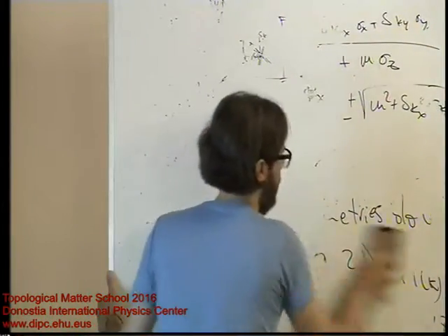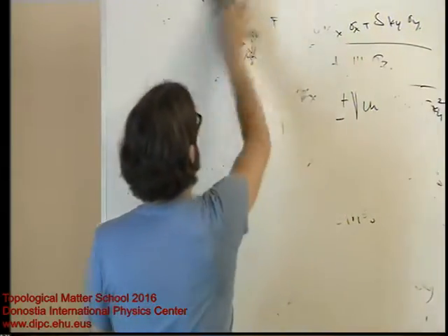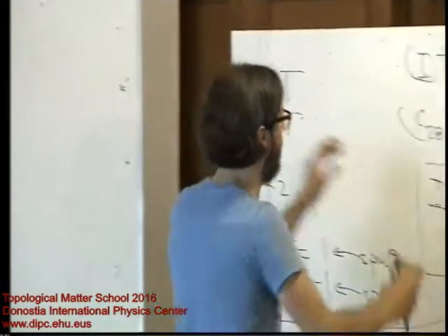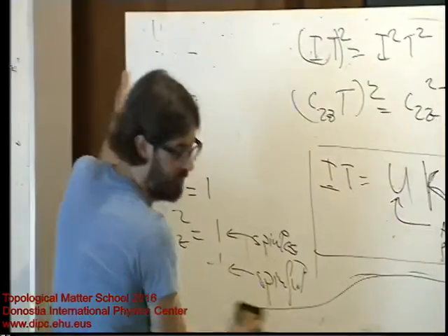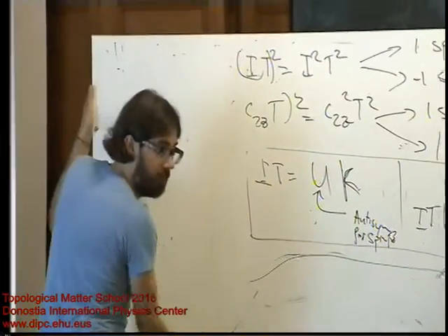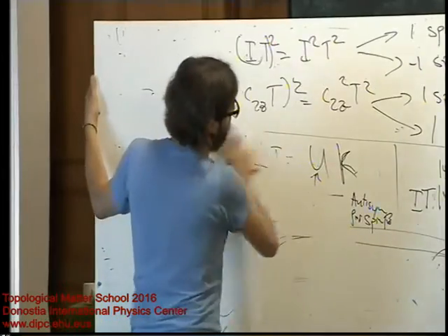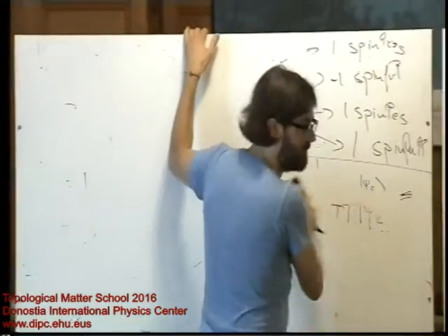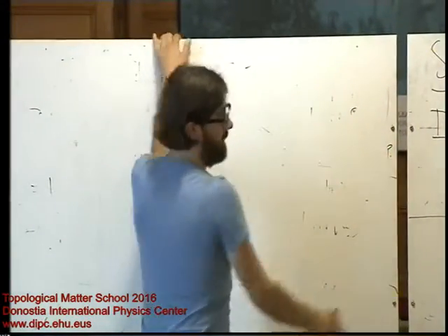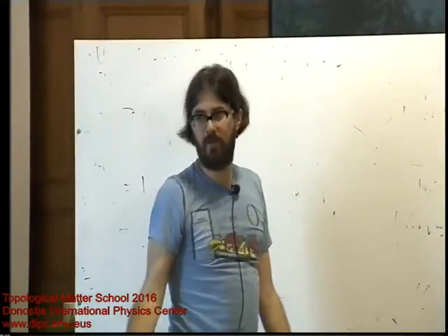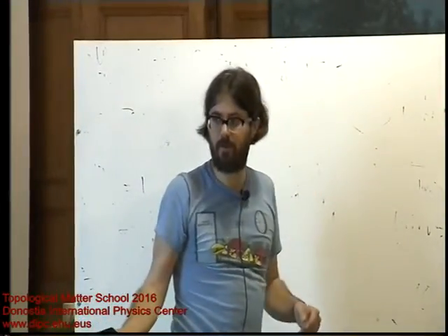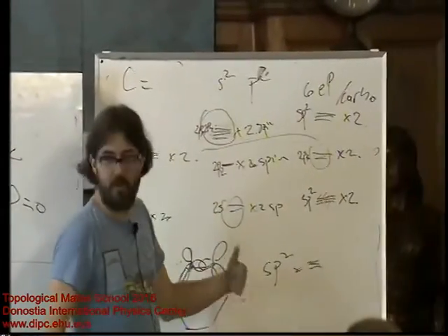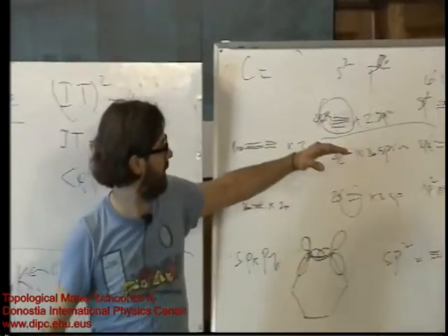So now that I know that my Fermi level sits in the pz orbitals, in the middle, this is not a matter of convention. This has to happen if I have sp2 hybridization, and sp2 hybridization is the chemistry content of this problem. Everything else is group theory in graphene. The chemistry content is that chemists tell me that carbon atoms sp2 hybridize. If the S level of the carbon atom was much lower than the P level, it wouldn't sp2 hybridize. You'd have an insulator. If carbon somehow had the S orbital much lower, sitting here, it wouldn't hybridize. You'd have your Fermi level sit here.